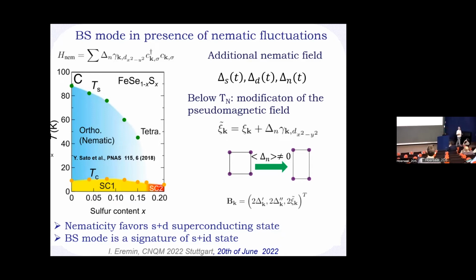If you are in the linear response, the signatures of the nematic and Bardasis-Schrieffer modes will still be very different, because what you know is that nematicity naively would favor a state which is an S plus D state, where you break the tetragonal symmetry and make it orthorhombic.